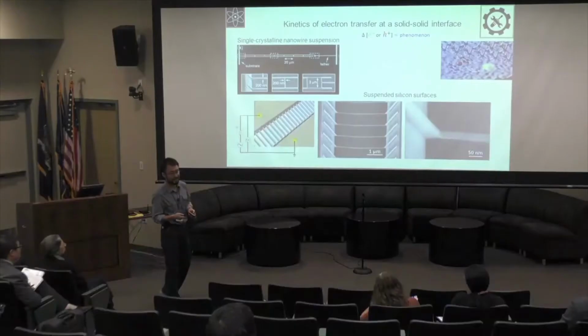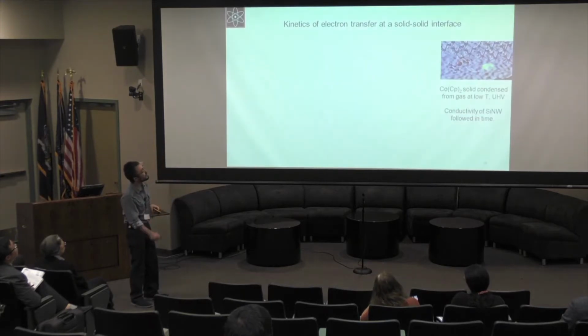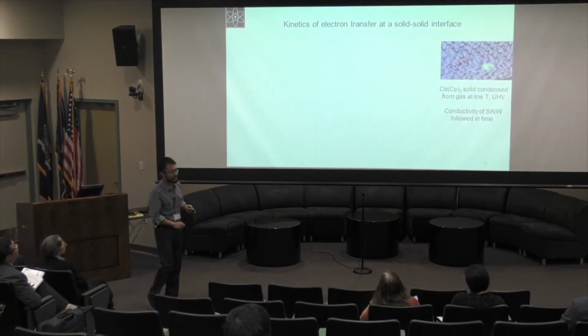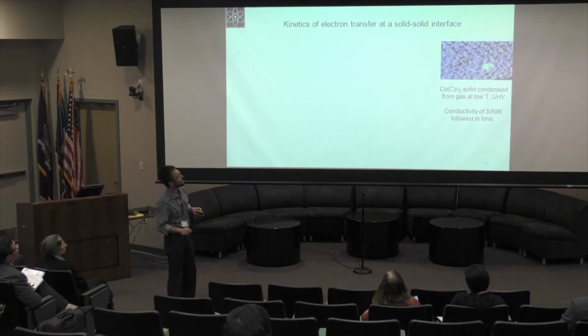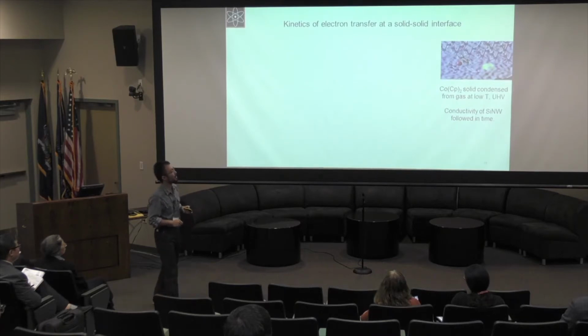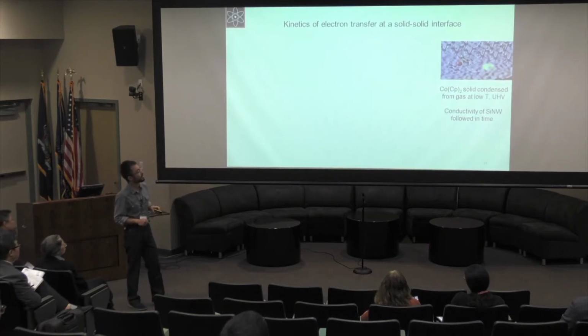And it's nice to make them very thin. So in the end, they're basically suspended silicon surfaces. And that's ideal for investigating interface phenomena. So we made those devices. We condensed cobaltocene, which is the electron donor, onto the devices at low temperature under UHV conditions. And we just followed the conductivity of these wires in time.